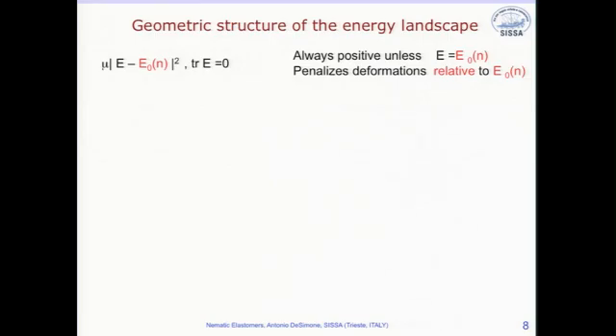Now, how does this work? So we've already seen this. So I was telling you that the spirit of the coupling, the key aspect of the coupling between elasticity and nematic direction is that the nematic phase transformation induces a spontaneous state of distortion, the one the material would like to have, and the energy is the difference of the deformation with respect to that. Before we had to do a complicated construction with composition with inverses. Here you get, as if you were doing plasticity in linear strain, the relative deformation with respect to the preferred one. It's a difference. And the energy is just the modulus of this relative deformation square.